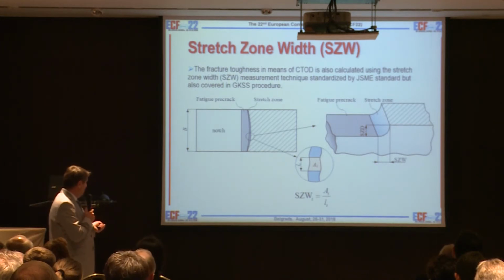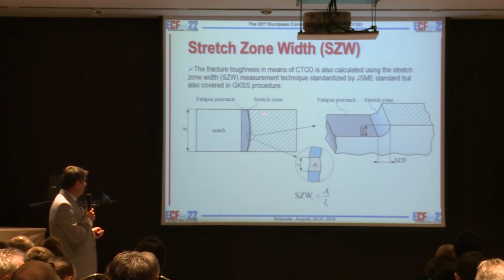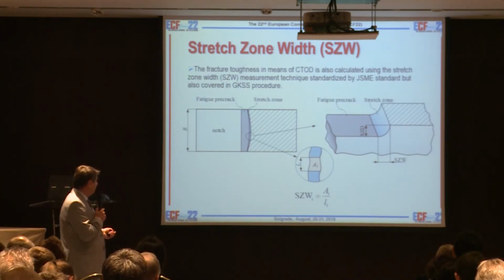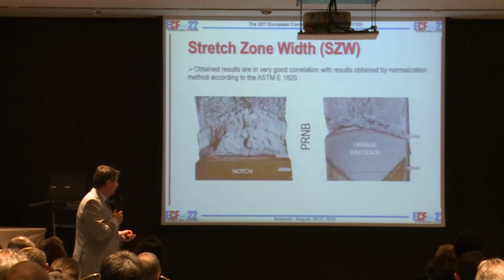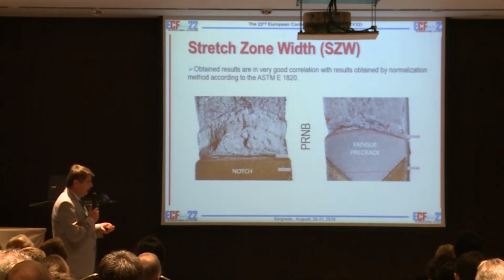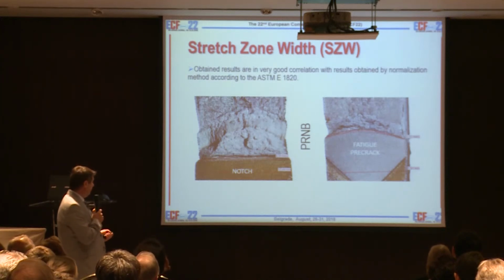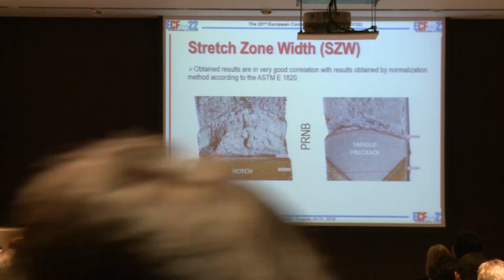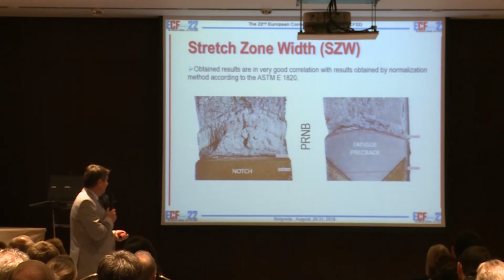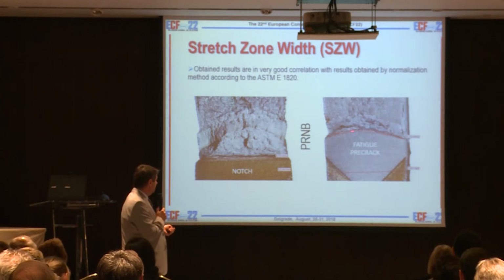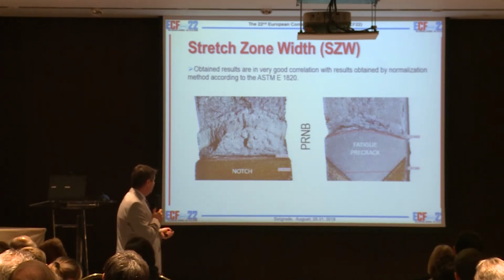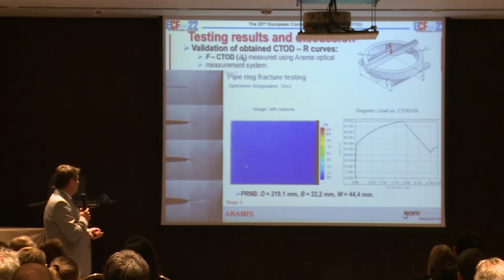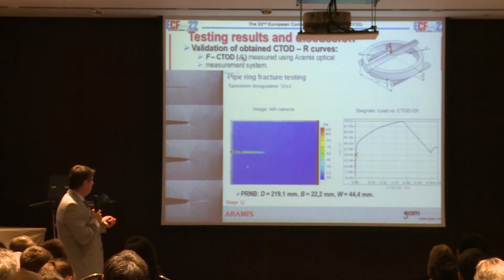We also measure the stretch zone width when we have the fatigue pre-crack in the single edge bend specimen, in order to determine the blunting line, because we also want to see if the blunting line from three-point bending can be used for pipe rings too. So here you can now see the notch. When you have the notch, there is higher contraction of material. Here is the stable crack propagation, this is the final. And if you have the fatigue pre-crack, this is the blunting, and then here is the final crack propagation.